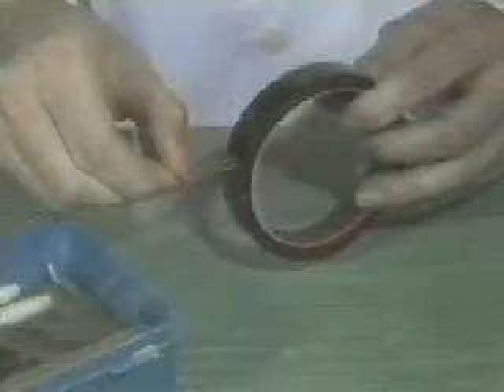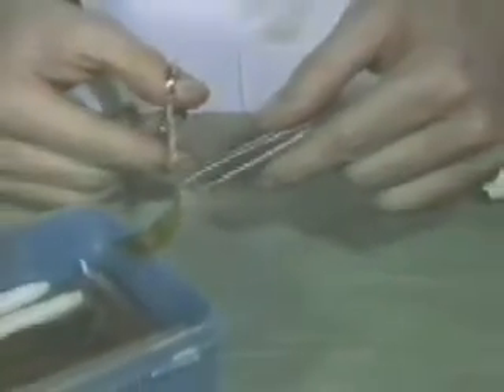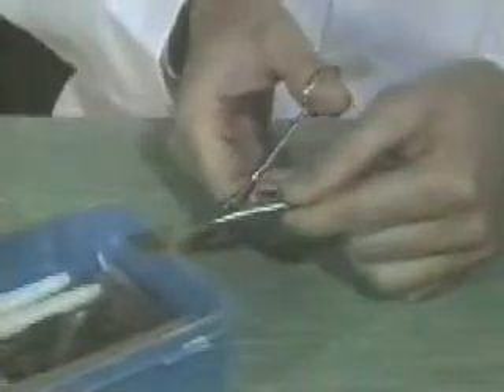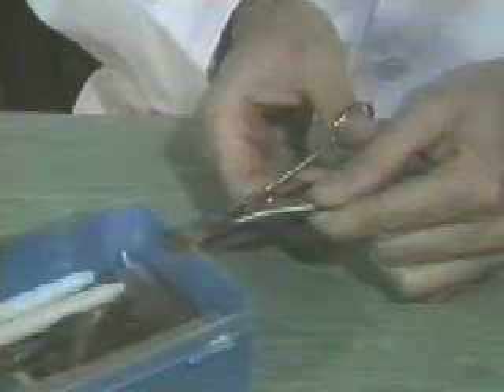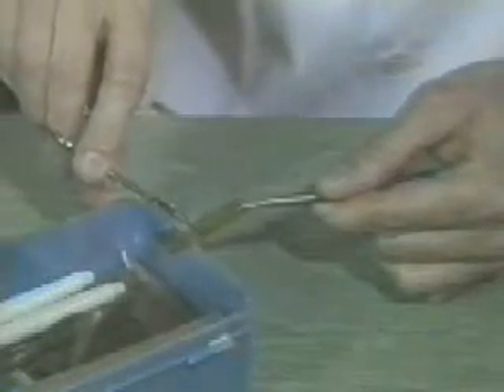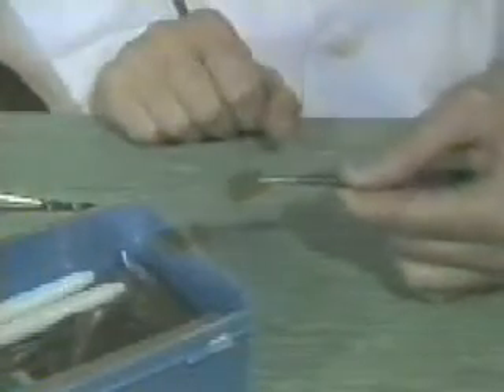A piece of adhesive is cut off. Only hold the adhesive tape with the tweezers. The yellow adhesive tape is heat resistant, and therefore it's also suitable for hot curing installation. Standard transparent tape is often used for cold curing so that the axis markings for positioning are more easily visible. The strain gauge is fixed.